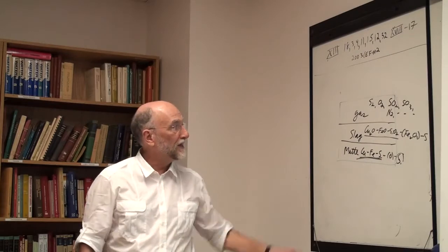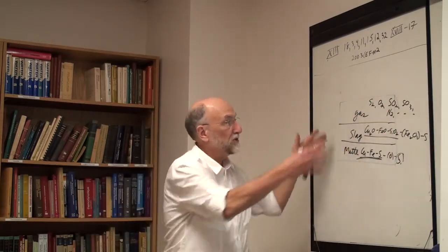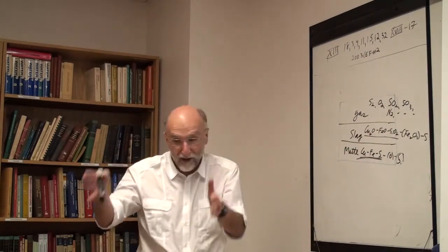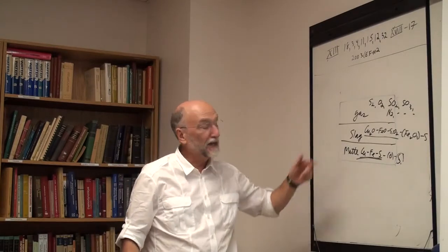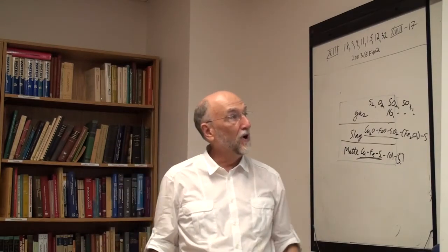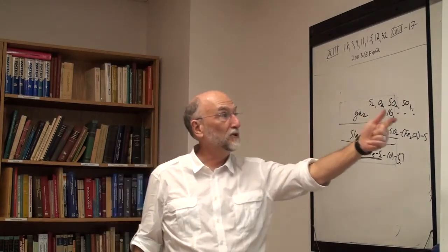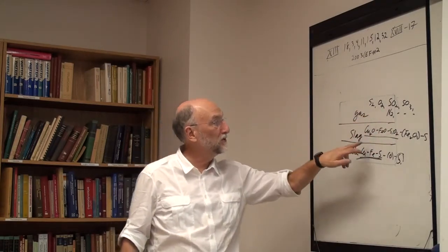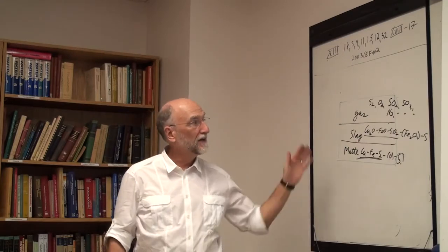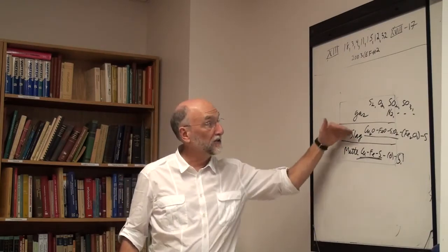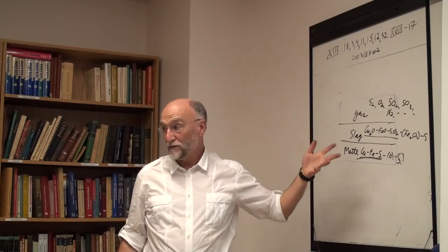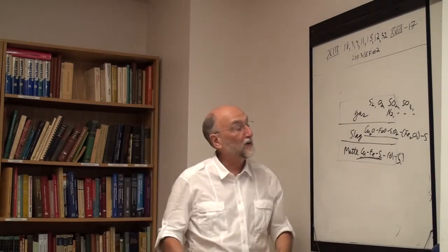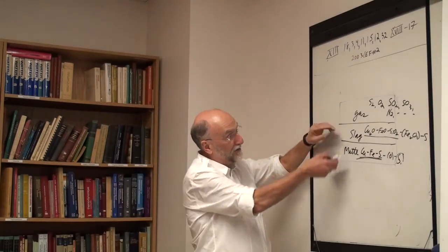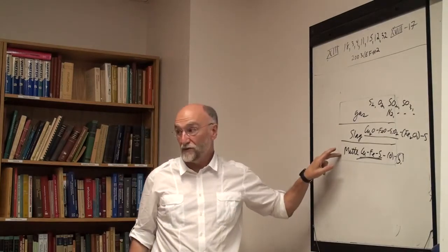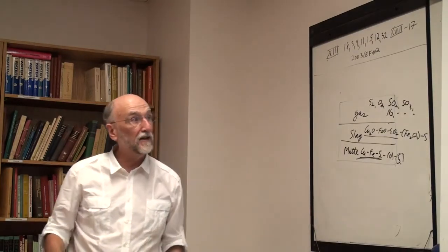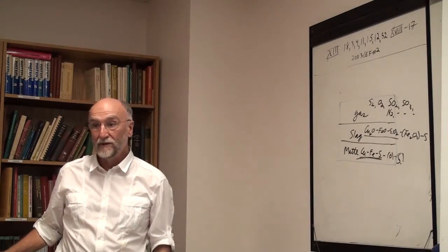Or let's put it another way. Say you have two systems, one furnace here and another furnace here, in which you have gas, slag, and matte in equilibrium, and both furnaces have the same temperature, same total pressure, same PSO2, same PO2, and the same sulfur content of the slag. Are the two systems identical in terms of composition, or could they be different? Remember, identical in composition doesn't mean identical in amount. You could have different amounts of the phases. I'm talking about the composition. The total amount of a phase is not a variable in the sense of the phase rule.